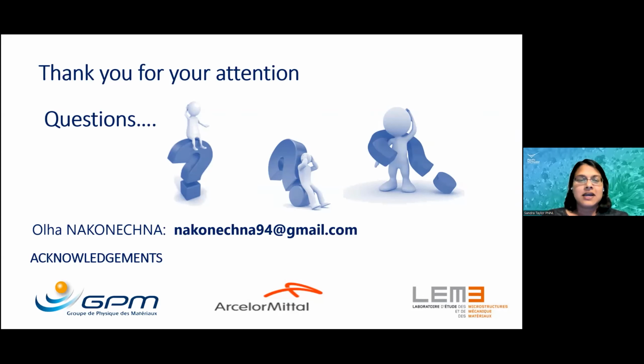Nice presentation. I had a question about your solute drag models, where in slides 21 and 22, you showed the results of how the models are predicting qualitatively similar manganese profiles. But you mentioned that quantitatively, the descriptions don't quite match. And so I was wondering what additional information it would take to get the models to match with the APT data. So indeed, one of the main parameters used in this solute drag-based model is the binding energy, the interface thickness.